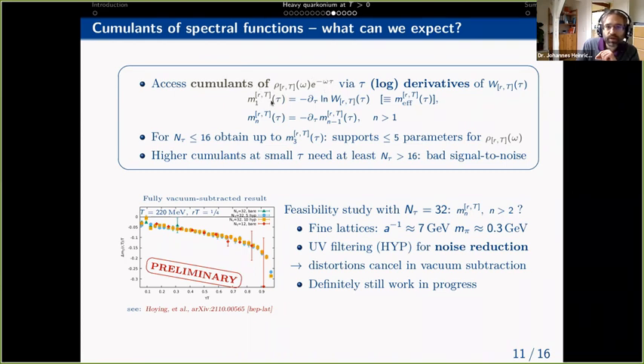And the first cumulant is just the standard effective mass in lattice QCD, which is usually plotted. And then we can just take higher derivatives of this to obtain higher cumulants. And at this point, we have not put any assumption in there. The typical picture of this first cumulant, once we subtract the UV contribution, is essentially linearly decreasing at small times and then starts to bend down very rapidly due to this infrared tail.